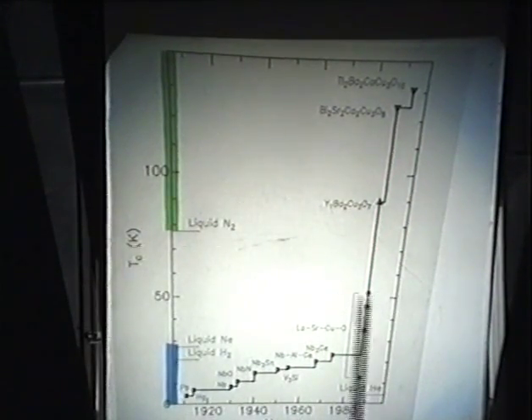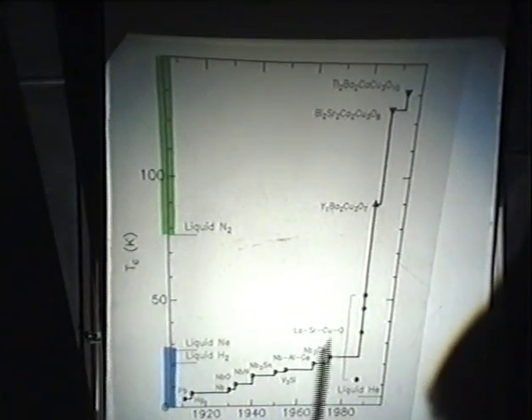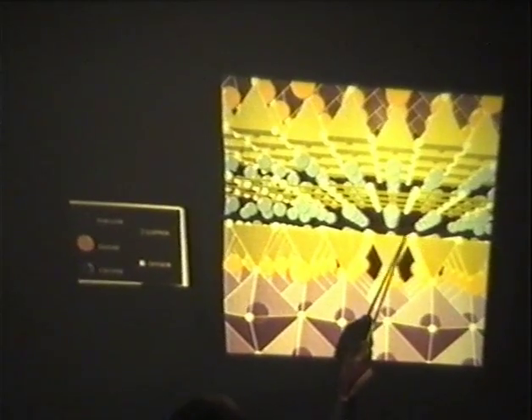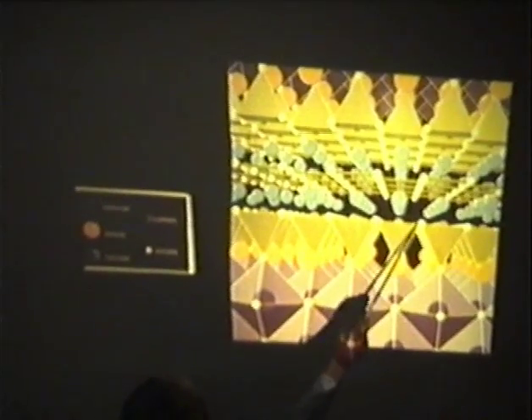And then by optimizing the stoichiometry, by optimizing the compound, they soon pushed the critical temperature up to above 50 Kelvin, which would have been miraculous for a metal. It was absolutely astounding for a ceramic. And this picture over here gives you some idea of the structure. We've got a whole lot of copper atoms. These are these greenish ones down here, and they're surrounded by these pyramid-shaped structures of oxygen. These ones here are oxygens, they're the coppers in there, and there's another plane up here.